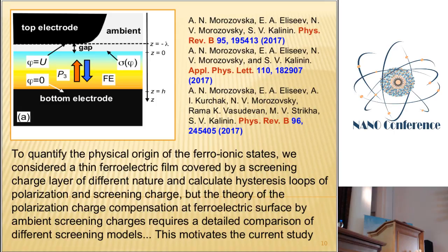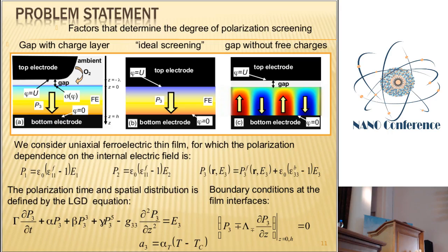And for this model, it is reasonable to consider, and to compare, three main models of the surface screening charges. The first is the linear screening. No screening at all: the model with perfect electrodes, which should be an ideal model leading to the smallest critical size. And the model with the gap and without surface charge at all, and this model should lead to the domain formation. To be brief, the mathematical description of the electric part of the problem is rather simple.